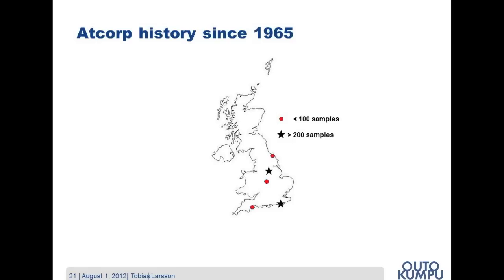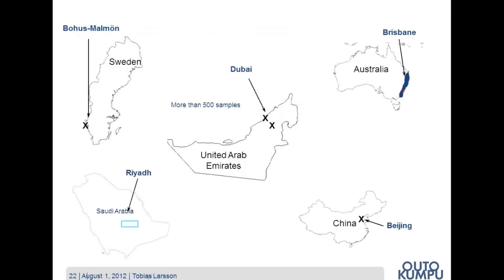We currently have over 500 samples exposed in the UK at various sites and hundreds of test panels in the US. But most of our atmospheric corrosion test data concerns austenitic and ferritic grades exposed in European environments. So the aim with our new atmospheric corrosion program is to supplement our knowledge with atmospheric corrosion testing in non-European environments. We currently have exposures at 5 new locations.